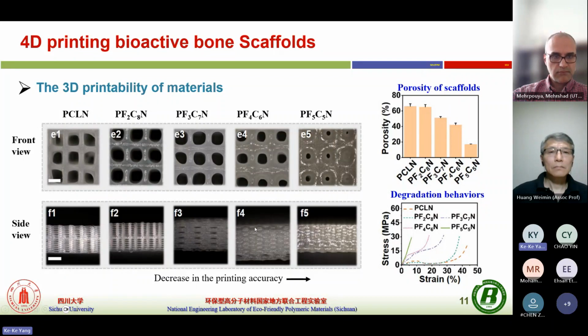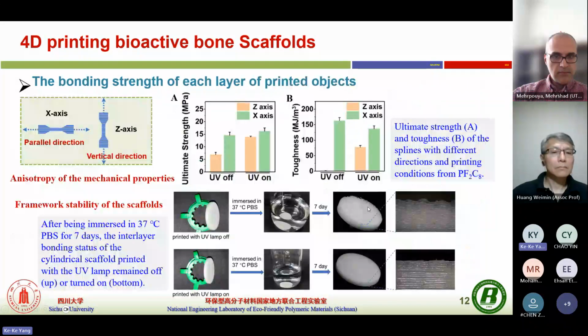Based on this, we optimized the structure to print the bone scaffold, and we also tested the binding strength of each printed layer, especially with UV irradiation.